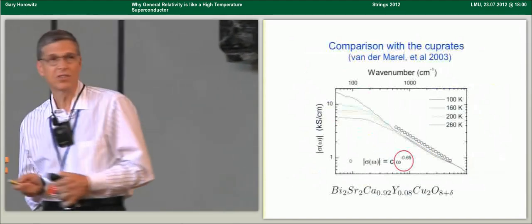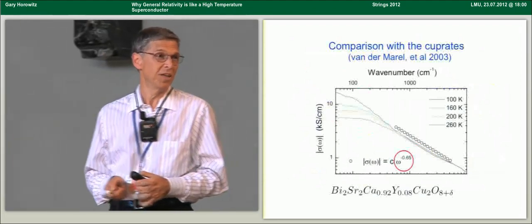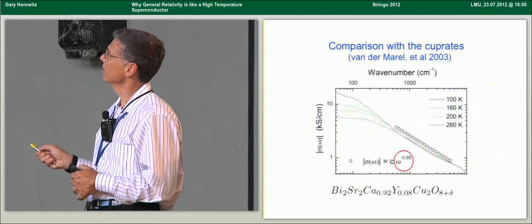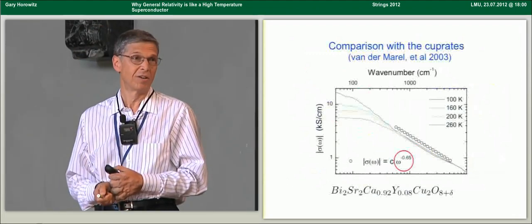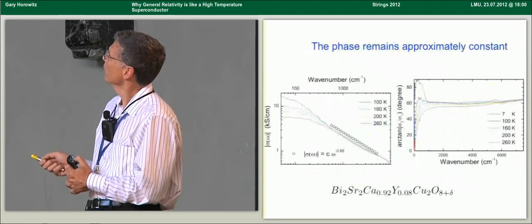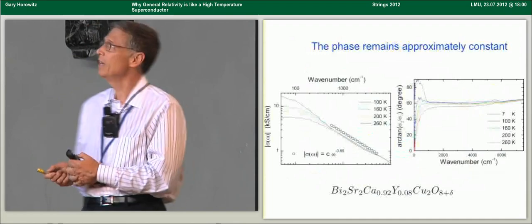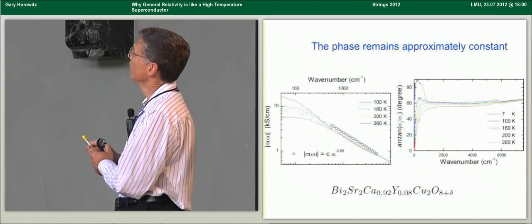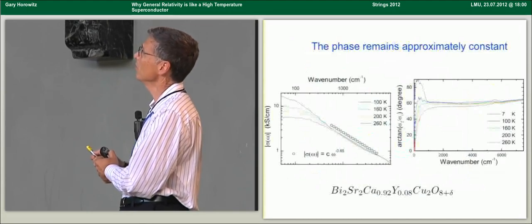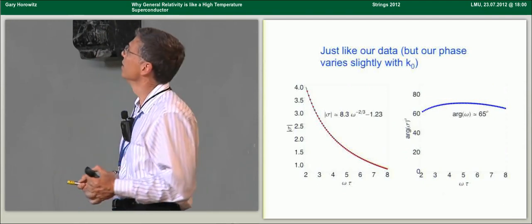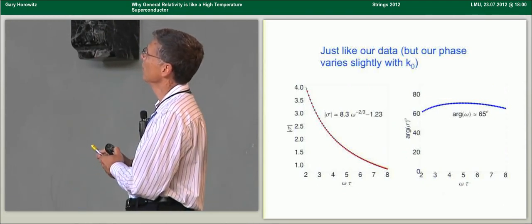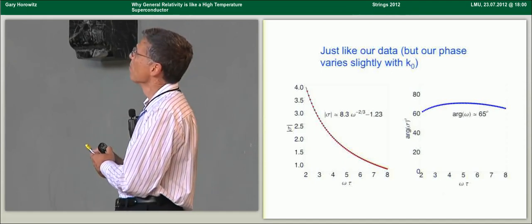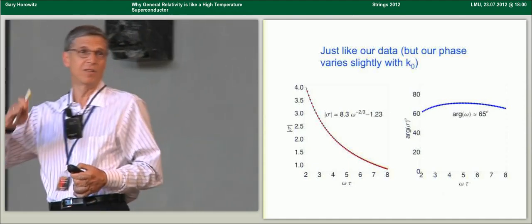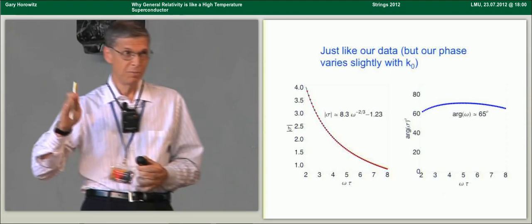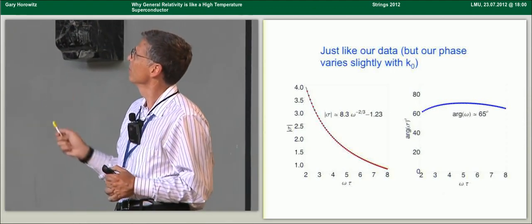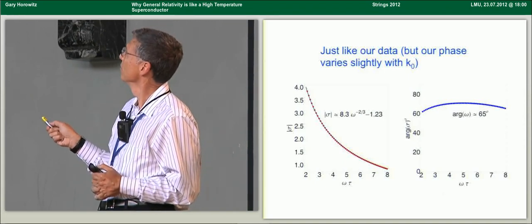In the theoretical condensed matter literature, I don't think there's an agreed upon explanation for why this optical conductivity has this 1 over omega to the 2/3 fall off. If you ask about the phase, the measured phase on this BISCO compound is given here. It's constant over this range of frequency at just 60 degrees. And I'll remind you that we get a value which varies somewhat, but is about 65 degrees. I should mention that our phase actually does vary slightly with K0. Unlike the power law, which is very rigid, very robust, this phase has slight variations and varies a little bit.